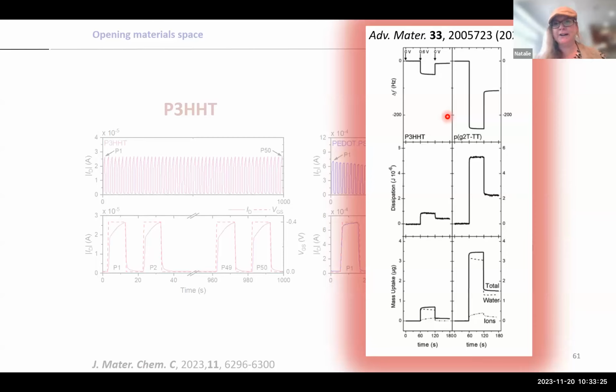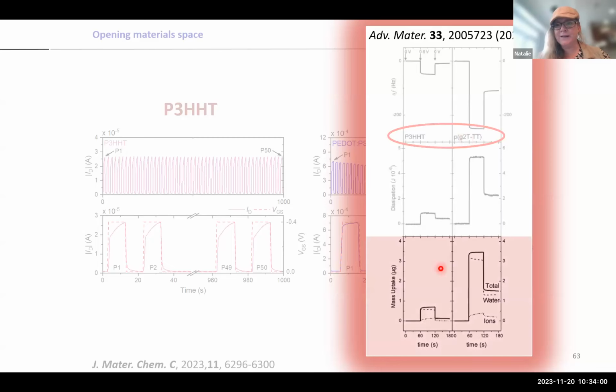And just to show here a similar example, so again, the P3HHT, we couldn't actually measure PEDOT:PSS. So this is quartz crystal microbalance measurements where we measure the mass change. We compare it then not with PEDOT:PSS, but the glycolated, so the G2T, these are PBTTT polymer as we use in SPECS, but with glycolated side chains. And really the key graph here is where from the QCMD measurements, we get the mass uptake.